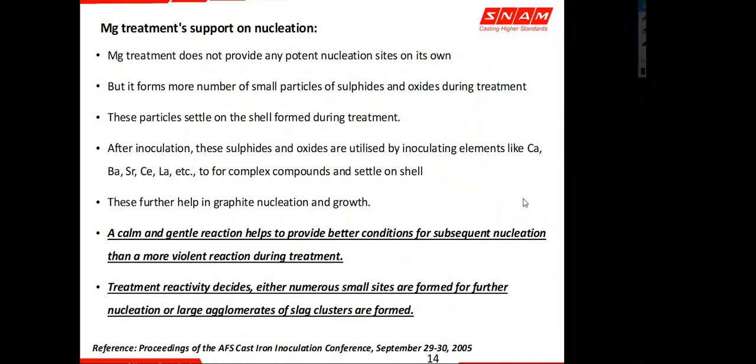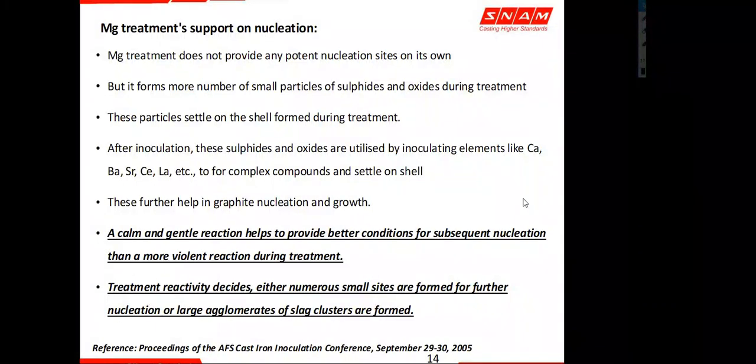As we know, there is aspiration, with oxygen coming in contact with the liquid metal and giving you agitation, and it gives you more oxide slags. So there is a possibility that high treatment violence can lead to more oxygen influx and more slag formation, and can also destroy the nucleation which is getting formed.